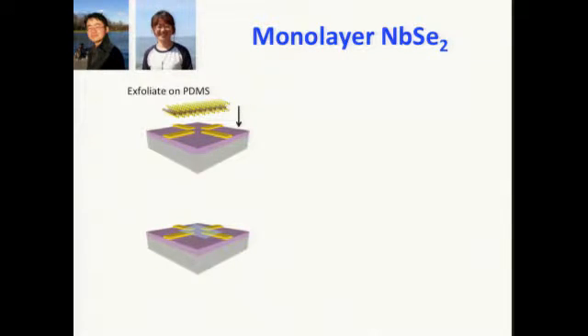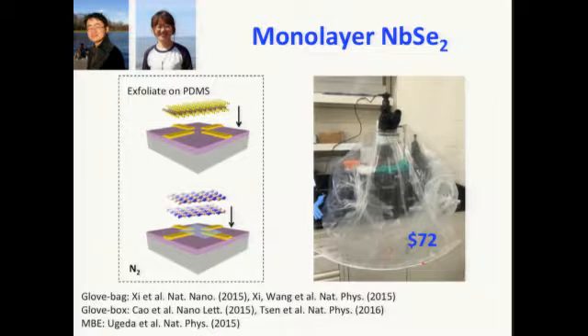So what we came up with is the following procedure, a simple technique to make devices. We first pre-pattern our electrodes into different shapes on the silicon substrate, and then exfoliate this material on flexible membranes of PDMS, and then align the two, stamp on it, and transfer a piece of material like this. And then to protect it from oxidation and contact with oxygen, we cover the material with a layer of boron nitride, directly doing another transfer and putting it on top. This is a lithography-free process, so we don't do much harm to the material. To further reduce the harm, we put the whole thing inside a glove bag filled with nitrogen, so that it's nice, and then we can make reasonable material.